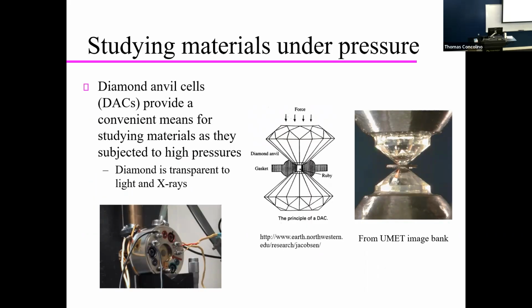through the diamond, through the sample, be diffracted, and out the side. Okay, so we're going through 4 or 5 millimeters of diamond here. Our sample cavity is 300 microns across. It really helps if you've got small, bright beams of high energy X-rays to do this. This should not be readily done in a home lab. Much better done